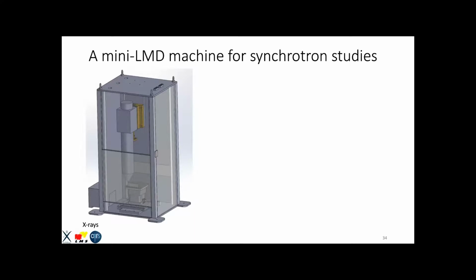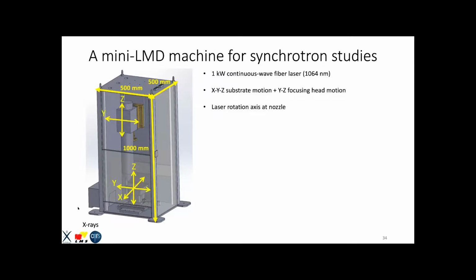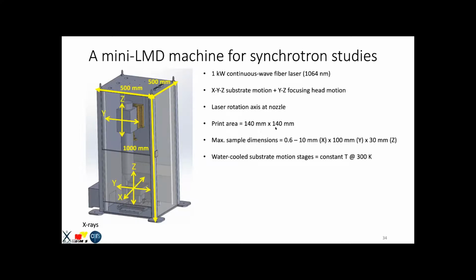Okay, so we have designed a mini laser metal deposition machine for synchrotron studies. This machine is 1 meter in height by 50 centimeters by 50 centimeters, equipped with a 1 kilowatt continuous wave fiber laser. The substrate has X, Y, Z motion. The focusing head has Y and Z motion. So we can do a combination of different printing techniques. The laser at the nozzle has a rotation axis, so it can always follow the direction of printing. So if you're going this way, the laser is here, then it rotates 180 degrees, and then it's here like that. The print area is 140 by 140 millimeters, and we can print samples in any direction we want.